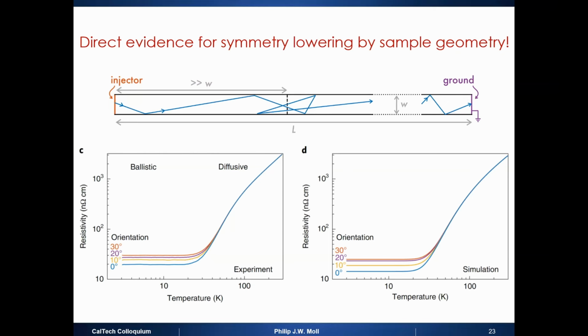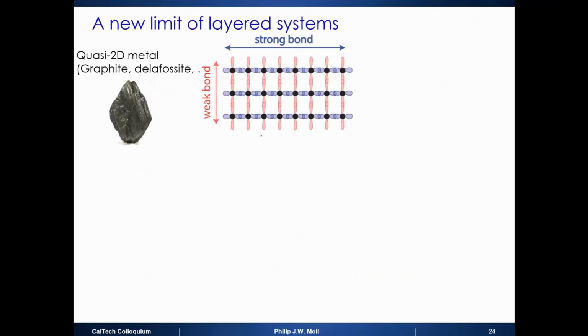Even the statistics you get from the rounding of this corner, which is of course not a mathematical hexagon, it's slightly rounded, we can discuss these details, gives you small deviations here. But in reality, what you get is two directions. One direction shoots electrons straight along the bar, and one where there's really no propagation along the bar. So that's what you can see as a result of the small shape and size of this object. That's what I find interesting about this. So this has been the start.